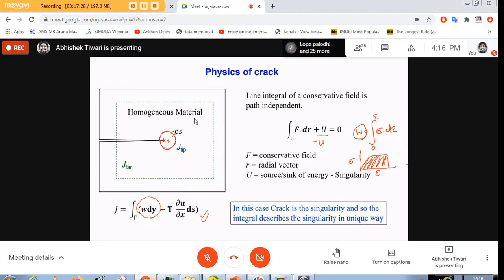Because this singularity is not changing, it is not growing. If we take the line integral here, or there, or along this green line, we will always get the same value because we only have one singularity, which is the crack tip, and that is embedded in all those line contours. And that gives a very good advantage to us: because we cannot measure anything at the crack tip, this path independence of this integration allows us to measure the properties at a remote location and relate it to what is happening at the crack tip.